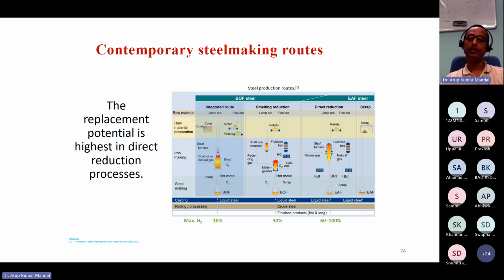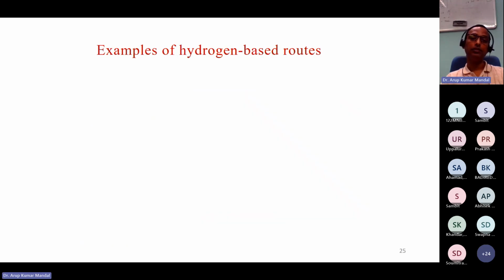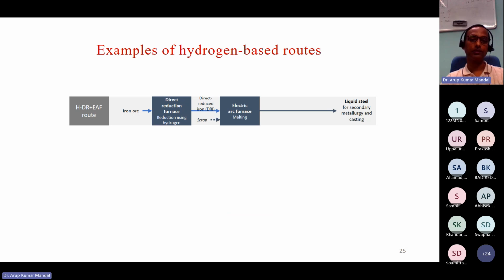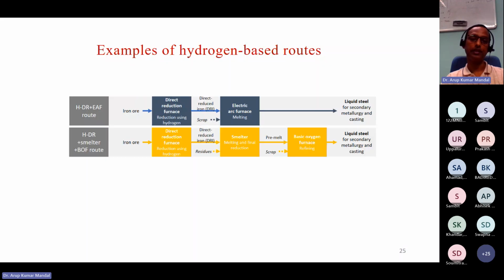Therefore, the major research which is going on is the hydrogen-based DRI process. There are different hydrogen-based DRI routes, like hydrogen DRI melted in an electric arc furnace. It means iron ore will be directly reduced using hydrogen to make HDRI, hydrogen-based DRI. And it will go to the electric arc furnace for melting to produce the liquid steel. Another option is that this hydrogen-based DRI can go for a combination of smelter as well as the BOF route. You can again produce the liquid steel.